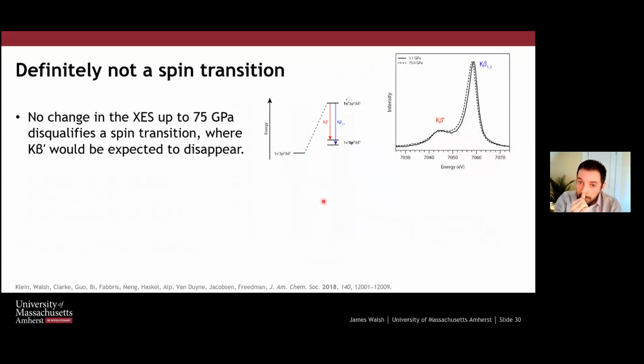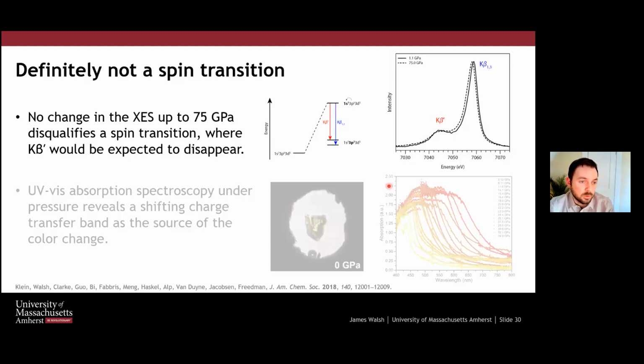We used many techniques, but the one that really shows this is X-ray emission spectroscopy. What we see is that over the course of compressing up to 75 GPa, there are many spectra that I'm not showing here, I'm just showing the two extremes because it illustrates the point. But we did collect many spectra at Sector 16, HPCAT, with Yuming Zhao and Paul Chow. What we see is basically no change. And that's a sign that we don't have a spin crossover, because we would expect this K beta prime peak to disappear if we did have a change in the spin configuration. So that kind of rules out this being a spin crossover. In fact, both transitions are not spin crossover.